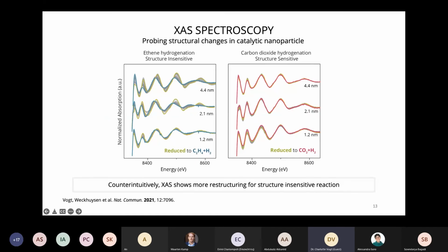Then we move to X-ray absorption spectroscopy, which is a really good way to probe structural changes in our catalyst nanoparticle. Local geometric changes around the average absorbing atom, around the average nickel atom, let's say. Not just that, we can also observe oxidation state changes, of course, more in the XANES region, more in the beginning part of these spectra. But basically, if you're going farther and farther away, if you're looking at these wiggles at higher and higher energy, you're starting to look at the effects of local geometry.